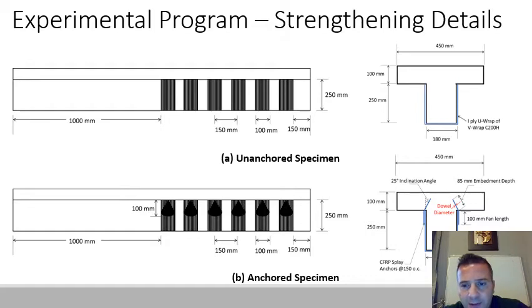As you can see here, this is the side that is strengthened. This is the unanchored specimen. This one is the anchored, and here we have the splay anchors, embedded inside. The inclination angle from the top is 25 degrees, so the angle from here to here is around 155 degrees. The fan length is 100 millimeter, the one that we adopted, and the dowel diameter is variable. The embedment length for this inclination is 85 millimeter.